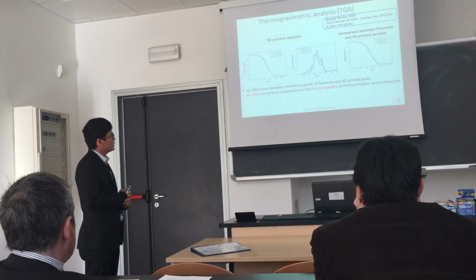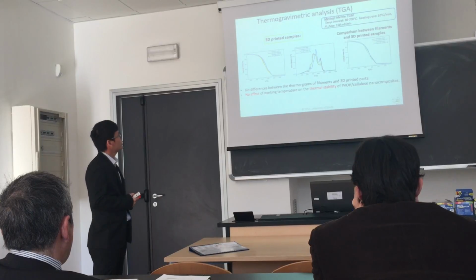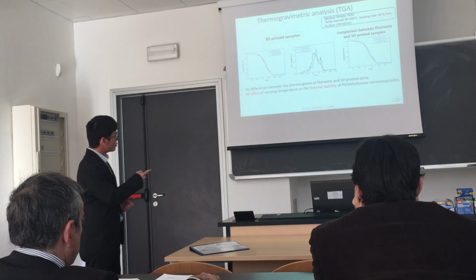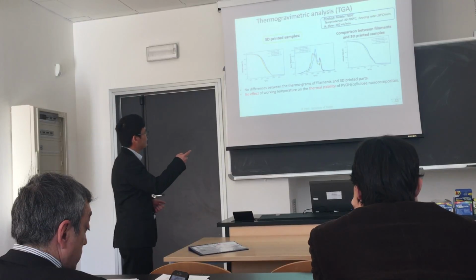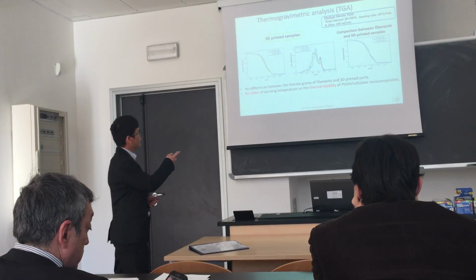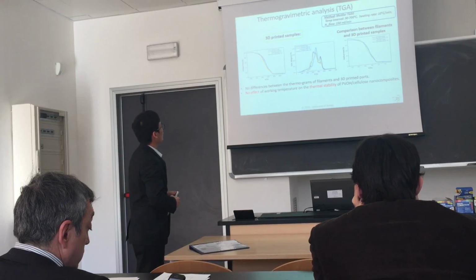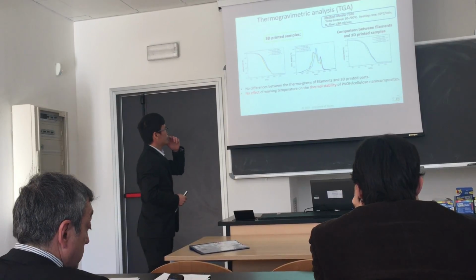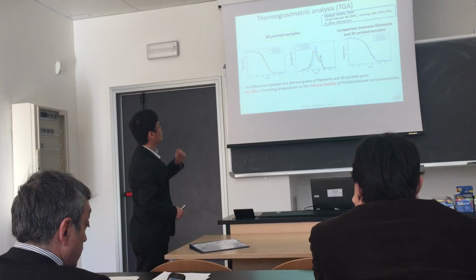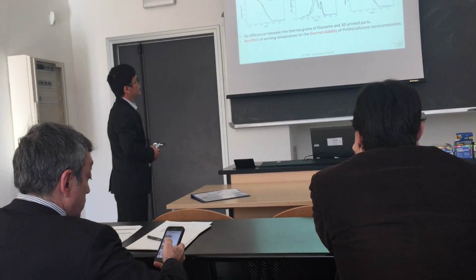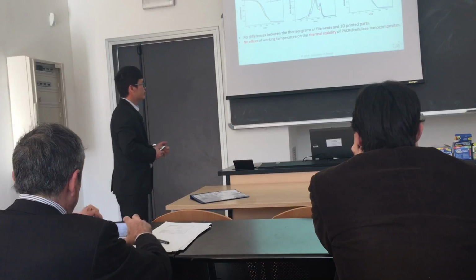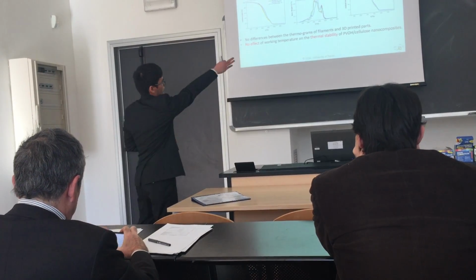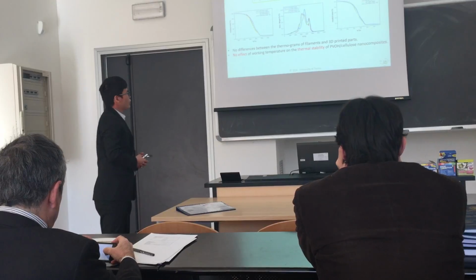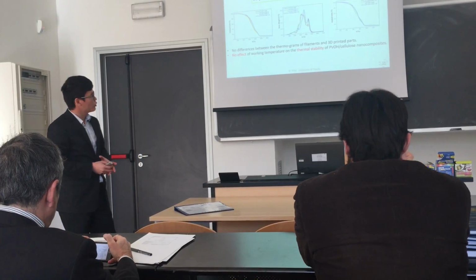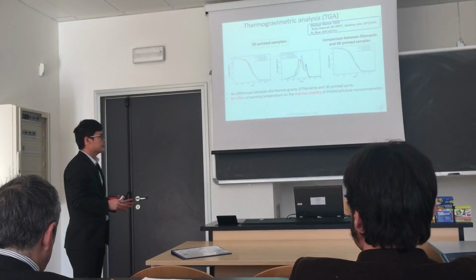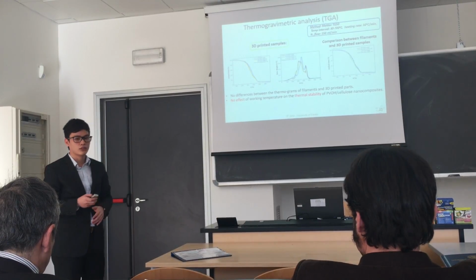And this is also the TGA thermogram of the 3D printed sample. We also clearly see the increase of the thermal behavior with the increase of the maximum degradation temperatures. We can see this from the derivative thermogram. And taking into account the comparison between the filament and the 3D printed samples on the right side, there was no difference between them, and so we can conclude that there were no effects of the working temperature on the thermal stability of the nanocomposites.